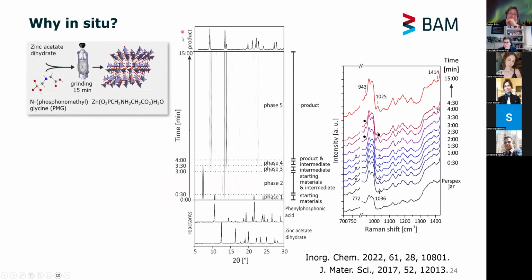So first things first, it's a fast reaction. It takes about 15 minutes for completion. And you can see here at around 4 minutes, they have the product phase. We could have stopped, to be honest. And you can also see the intensity doesn't change very much. So that's done. The reaction is finished. If we look down here, then we see a period where we can see the starting materials. And then there is a formation of an intermediate. And then you see intermediate and product, and then pure product phase.